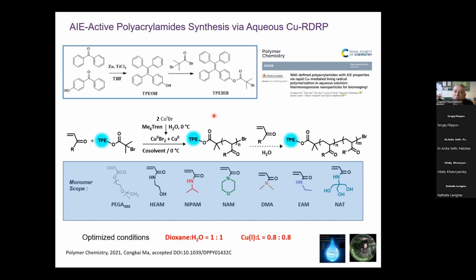The previous slide was about doing this with relatively hydrophobic monomers. Now we're going to do acrylamides, so acrylamides and water-soluble acrylates. Same principle. We make our initiator, but we now do that disproportionation. We take our copper-1 bromide and disproportionate it with hexamethyl-TREN and water, typically in ice, but it doesn't really matter. Especially when we're doing NIPAM, we don't want the exotherm to precipitate it, so we remove the heat.